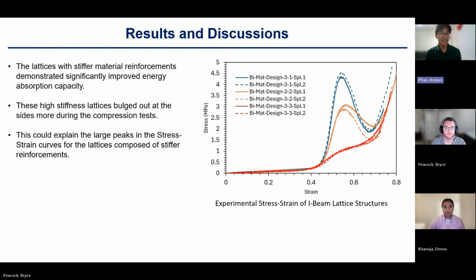Results and discussions. The lattices with stiffer material reinforcements demonstrated significantly improved energy absorption capacity. These high stiffness lattices bulged out at the sides more during the compression tests. This could explain the large peaks in the stress-strain curves for the lattices composed of stiffer reinforcements. On the right are the experimental stress-strain curves for the lattice structures.